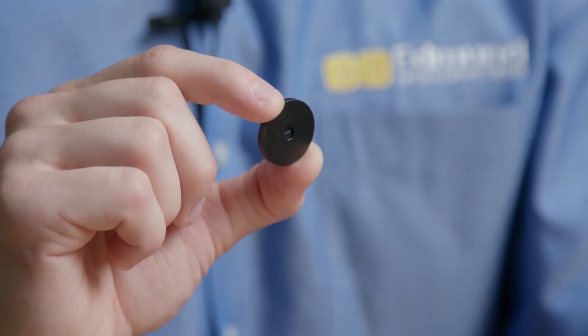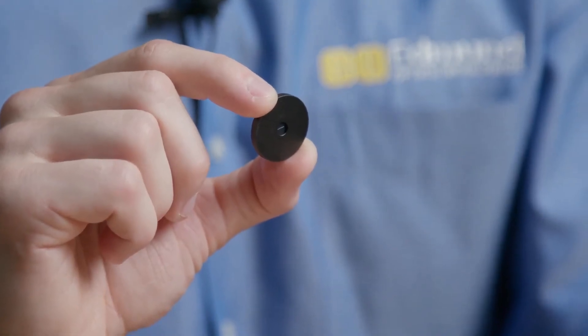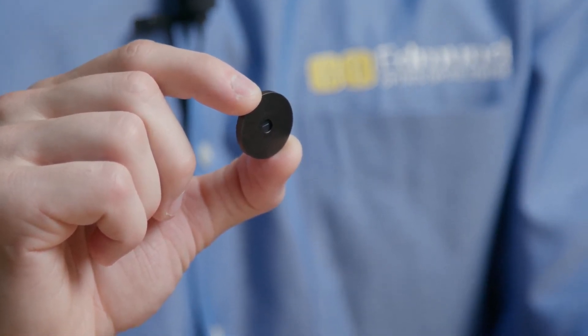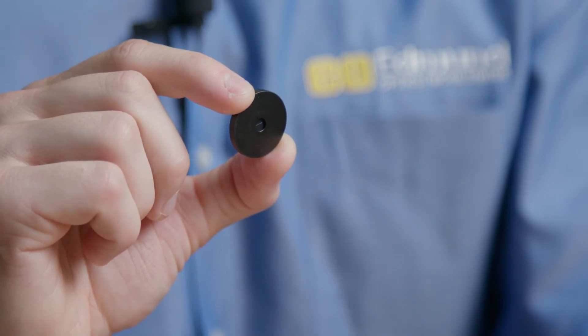Acktar Black pinholes and iris slits feature stainless steel substrates that are coated on both sides as well as on the edges with magic black. This coating provides wideband, lower reflectance from the extreme ultraviolet to the shortwave infrared, near-zero outgassing, and coating stability up to 380 degrees Celsius.